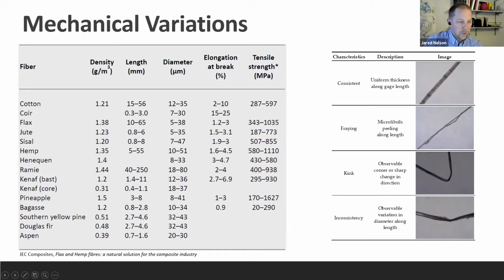Some of the things that contribute to those wide ranges are different characteristics and defects that we see. This is a nice, consistent, uniform fiber that my research group imaged a while ago when we were looking at specific defects and trying to identify them. We identified fraying, where we have microfibrils, and you can see these microfibrils peeling away along the length. And so we get variations in thickness. We basically get these little branches coming off, which don't really have much load carrying capability, and material properties get thrown off by those. We can see we have a kink here, where we have a sharp corner or change in direction. And then we have just general inconsistency, where we have changes in variation along the way.